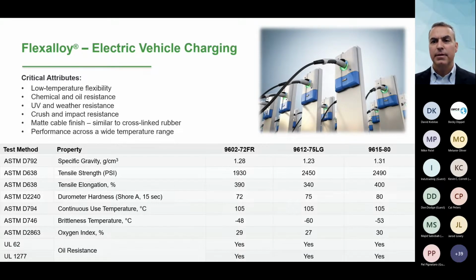Going on to the jackets. For EVE jackets, we suggest 3 compounds for consideration. The first column, 960272FR, is a workhorse compound with a minus 48 C brittleness temperature. The next one over, 961275 LG for low gloss, is our lowest temperature EVE compound. It's got a brittleness temperature of at least minus 60 C. And then Flexalloy 9615-80 is a bit harder. It offers greater durability and a brittleness temperature in between the other two. So you've got some choices depending upon how you want to make the design of your cable and the performance of that cable.